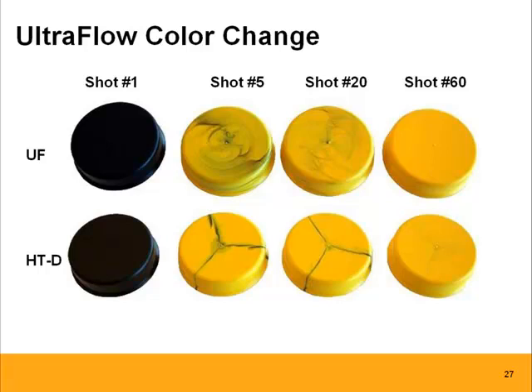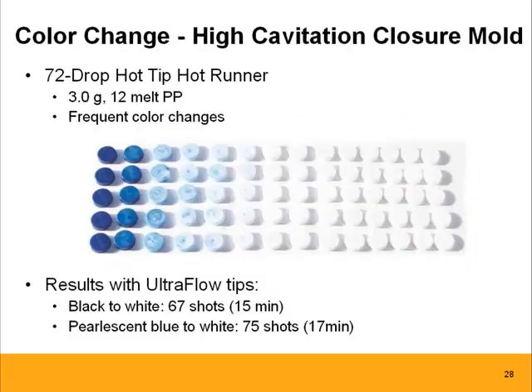I have an example for you here: a 72-drop hot tip hot runner, 3 grams, 12 melt polypropylene. Again, depending on the resins and depending on the colorants being used, every situation is a little bit different. But in this case, we have been able to achieve 15-minute color changes on a high cavitation hot runner system.